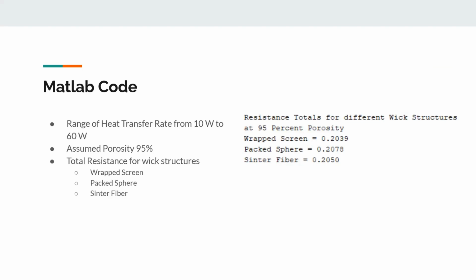For the MATLAB code, the original goal was to find the outlet temperature of the heat pipe given certain properties that were given. In order to find a range of the outlet temperatures, we assumed 10 to 60 watts for the heat transfer rate. This would give us a good starting point to see how the different wick structures would affect the outlet temperature. For the first test, we assumed the porosity was 95%. This gave us a total resistance that was close to the published results, which was 0.202. You could see that the wrapped screen, packed sphere, and sintered fiber are relatively close to that, and that was for 95%. Next slide.